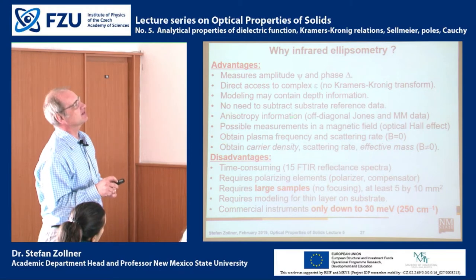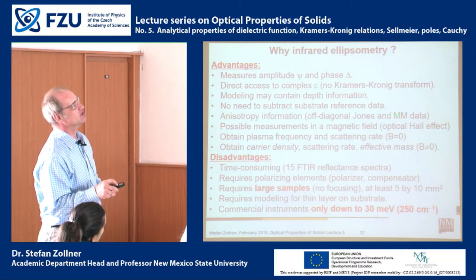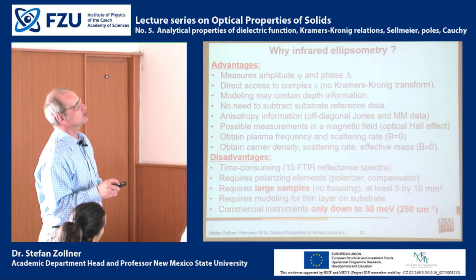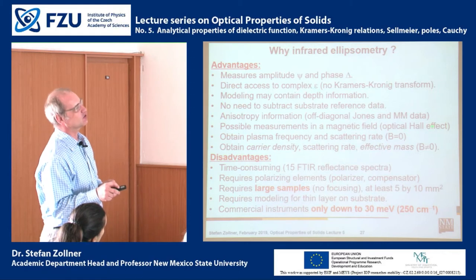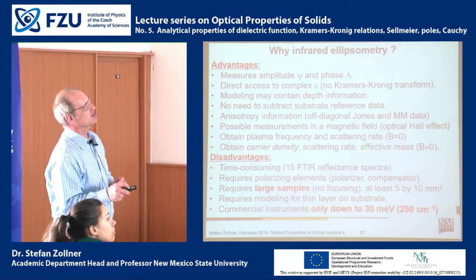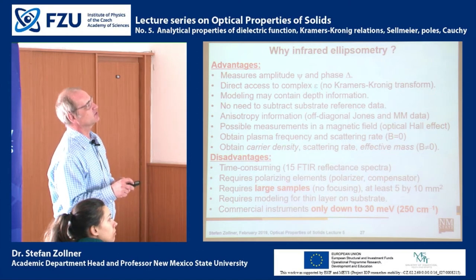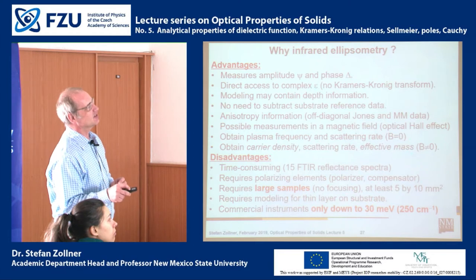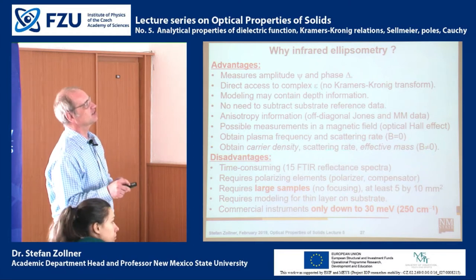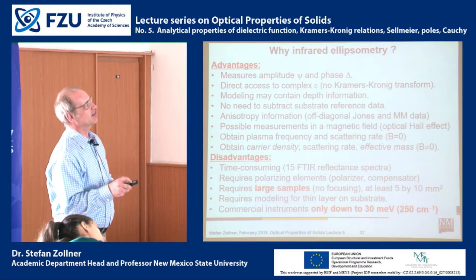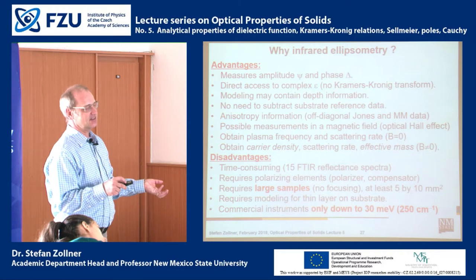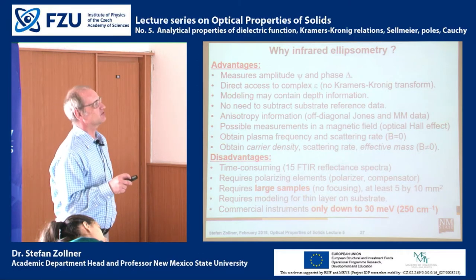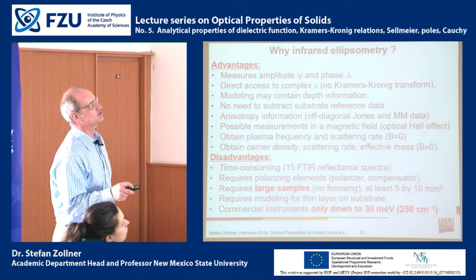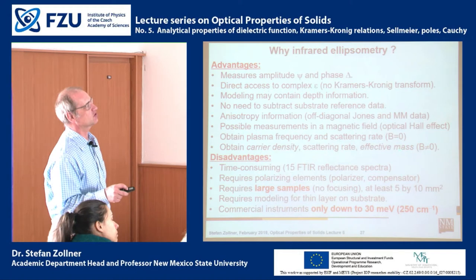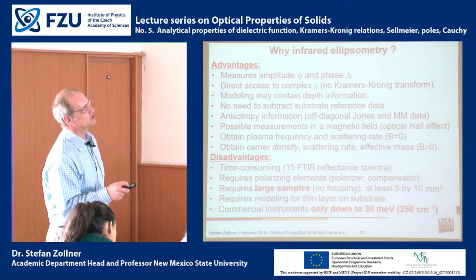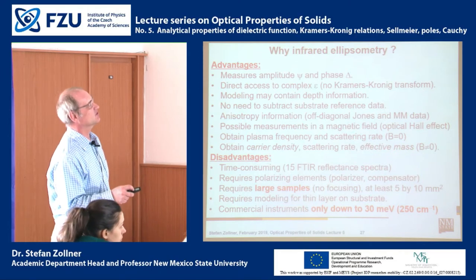We are able to get information about anisotropy from the off-diagonal elements. We can perform ellipsometry measurements in a magnetic field. That's called the optical Hall effect. And in the absence of a magnetic field, we can get the plasma frequency and the scattering rate. The plasma frequency has to do with the carrier density and the effective mass, but we cannot really separate the two. But by turning on a magnetic field, we get the additional Lorentz force, and that means from the plasma frequency, we actually go to the carrier density and the effective mass and the scattering rate.